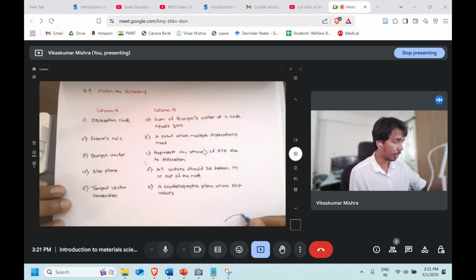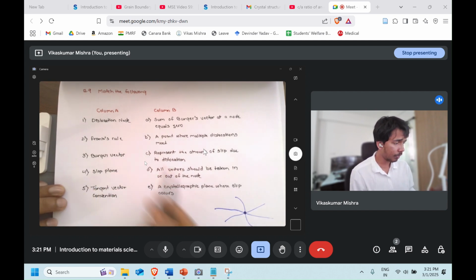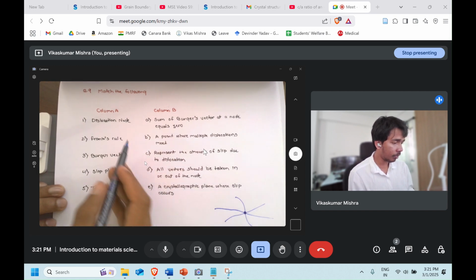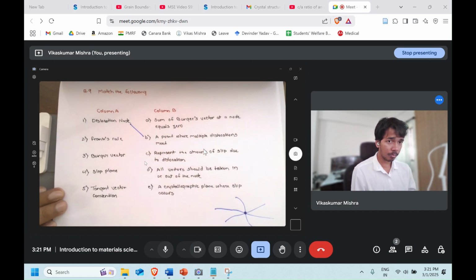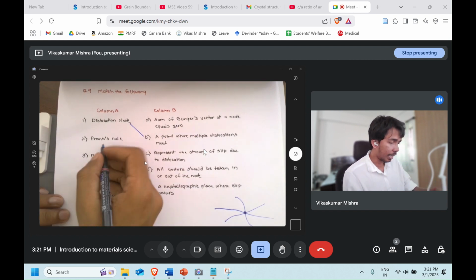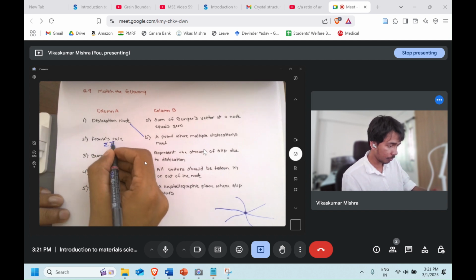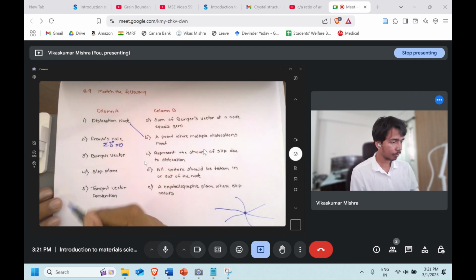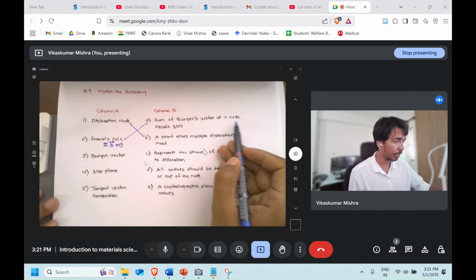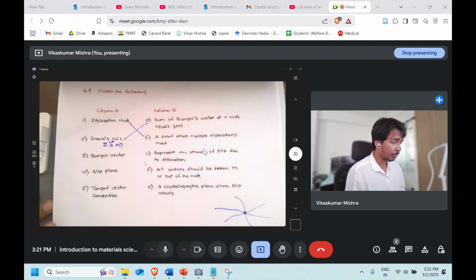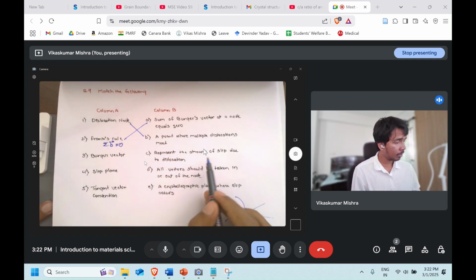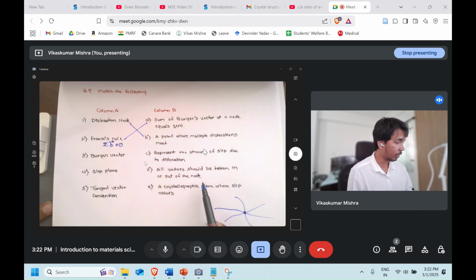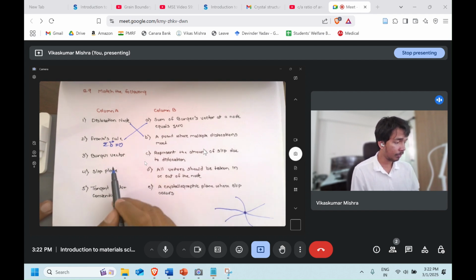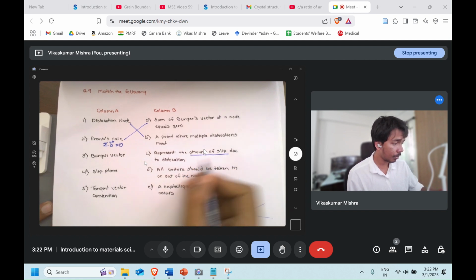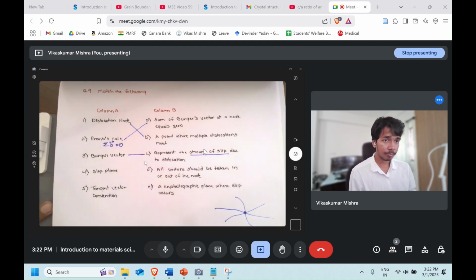If we have dislocation 1, let us say, dislocation 2, dislocation 3, this point is the one which is called a node. So we can say that a point where multiple dislocations meet is known as the dislocation node. Frank's rule: we know that Frank's rule says that the sum of the Burgers vectors at the node will be equal to 0. So we'll match 2 with option A. Now what is the Burgers vector? It represents the amount of slip due to the dislocation. We know a Burgers vector represents the amount of slip due to a dislocation. It will match with this.